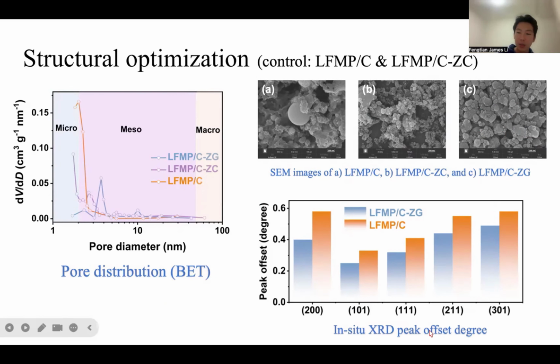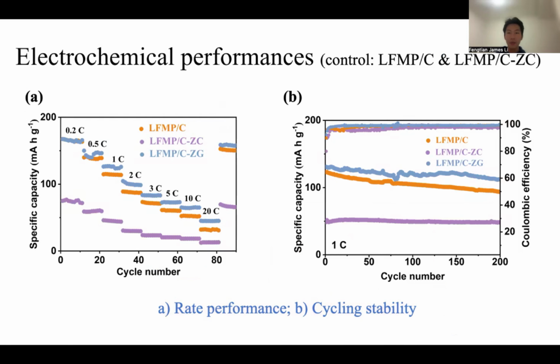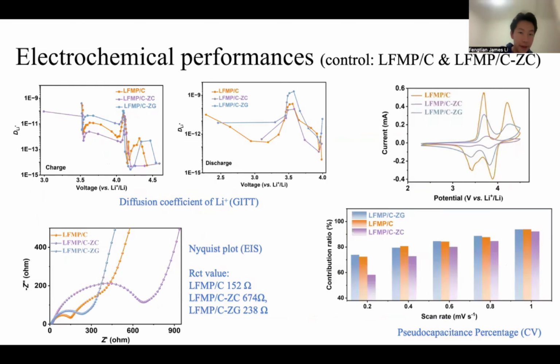The in-situ XRD peak offset degree, which is the crystal structure data collected during the electrochemical process, indicates that most structure of the ZG material is preserved, so it's structurally stable. Some more straightforward data come from the electrochemical performances. Under different rates of charge and discharge, the ZG material is the best within the three. And under continuous cycling of the material, the ZG material also is the highest performance one.